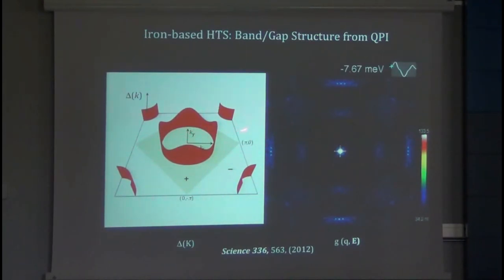It's different in different directions of momentum space, but it's not nodal. In most of the iron superconductors, there's no node. There's a zero, theoretically, in the order parameter along this line in momentum space. But the Fermi surface doesn't touch that line. And that turns out, we think, to have some very important consequences.